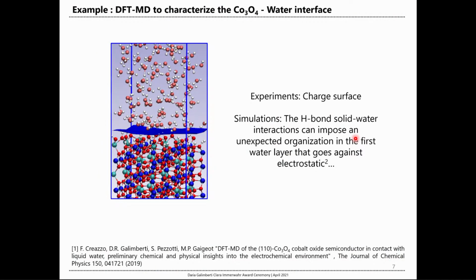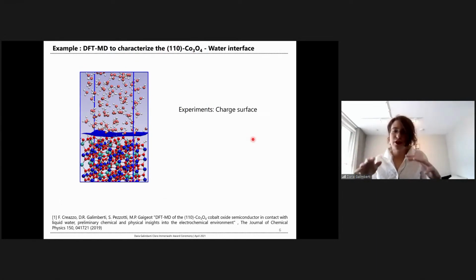But instead, something curious can happen, and simulation can tell you, that sometimes, especially when the positive surface is exposed, you also have a local rearrangement of the water, because this surface is also a really good hydrophilic surface. So water is really happy to make hydrogen bonds with it, and it's so happy that the water molecules that, following the field, should point the oxygen to the surface and the hydrogen towards the bulk of water, instead of being a good soldier and following this field, decide to flip up and make a hydrogen bond, generating an organization of the first water layers that is against what you would expect from electrostatics. And obviously, this will change how the oxygen evolution reaction will proceed and the energetics involved.